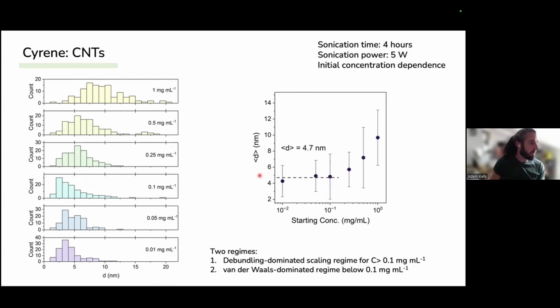So what we have here is a relationship between the diameter of the debundled nanotubes and the starting concentration. This suggests that there are 2 regimes here. One where it is debundling dominated scaling for concentrations above 0.1 mg per mL.